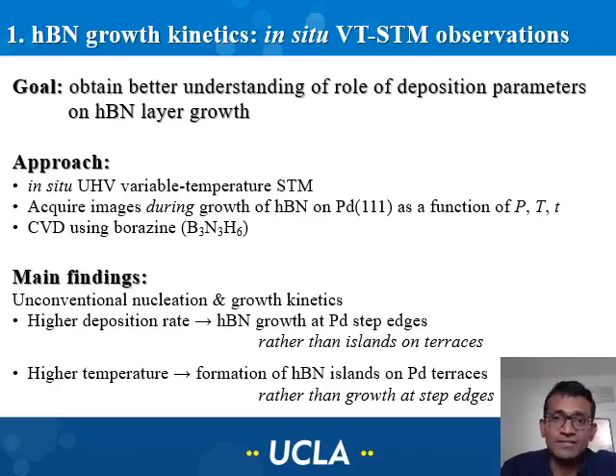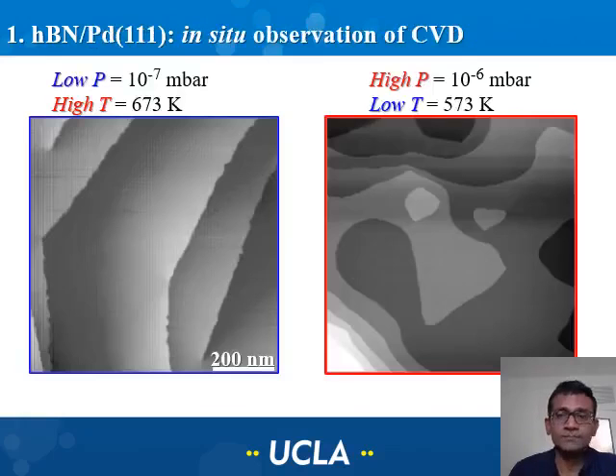And when we increase the temperature, we actually observe hexagonal boron nitride islands on terraces, whereas in conventional thin film nucleation and growth kinetics, one would expect increasing the temperature to result in growth preferentially at the step edges rather than islands. So basically what we observe is somewhat counterintuitive to what is expected for a typical three-dimensional layer growth on a single crystal.